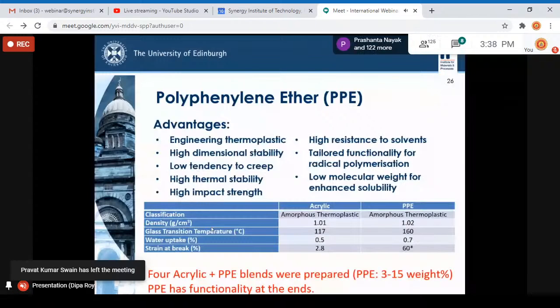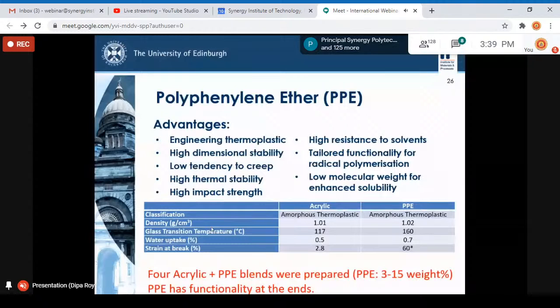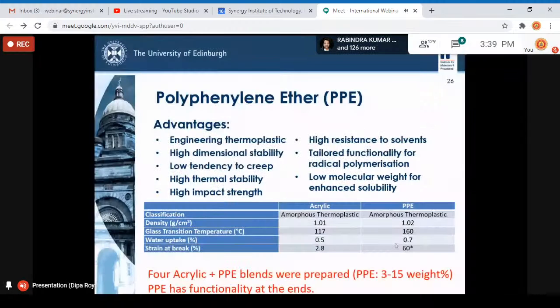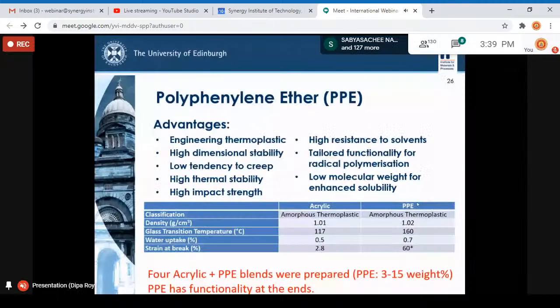Polyphenylene ether is an engineering thermoplastic, unlike acrylic, and it has a low tendency to creep and high resistance to solvent. So these are the main reasons why we selected an engineering thermoplastic. And you can see here the comparison of acrylic and polyphenylene ether. Compared to acrylic, the strain at break of polyphenylene ether is much, much higher. So although it's an amorphous engineering thermoplastic, it has a much higher breaking strain, which might be helpful for acrylics. And apart from that, the glass transition temperature of polyphenylene ether is 160 degrees, which would be helpful for enhancing the overall thermomechanical behavior of the acrylic matrix composite. So this was the main motivation why we selected polyphenylene ether. And it has got the functionality we wanted for reactive blending with the acrylics.